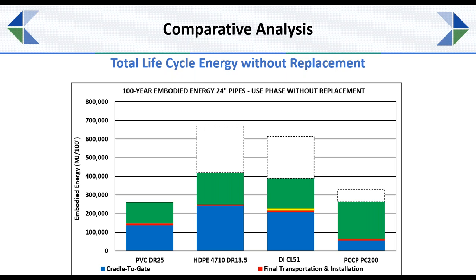So those materials that were less than 100 years, we did have to consider initially replacement of those materials and the extra energy required for replacement of those materials. But to put everybody on the same level, we looked at what the total embodied energy for the various pipe materials would look like if we took out the replacement. And they look like these values, what you see here without the dashed line. Even so, you see that PVC pipe does have the lowest embodied energy over the 100-year life cycle.